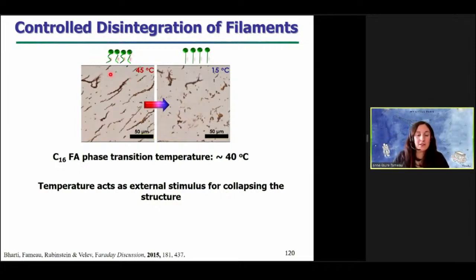So here you have an example of filaments that we produce at 45 degrees when the alkyl chains were in fluid state. We decrease the temperature below the phase transition. So you have now the alkyl chains in a gel state, and what you can see is that the temperature acts as an external stimulus because it just collapses the structure. You disintegrate your filament just by tuning the temperature.